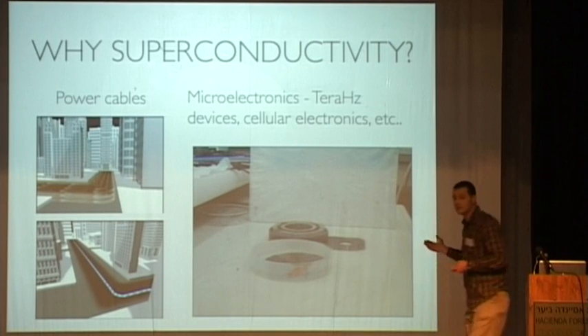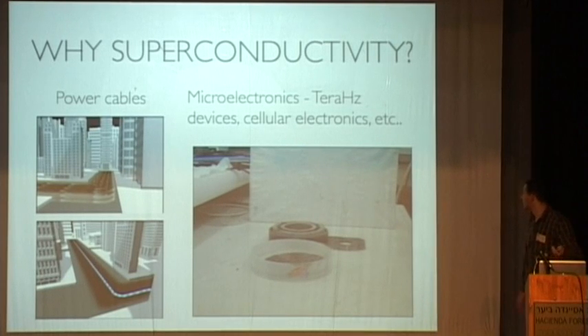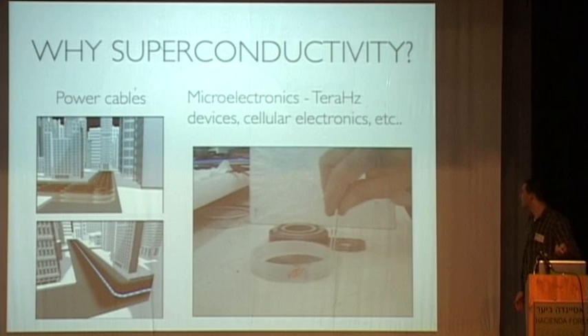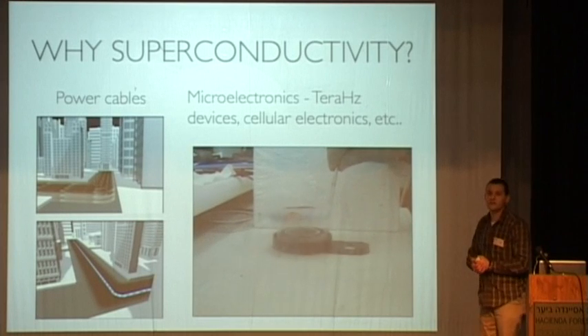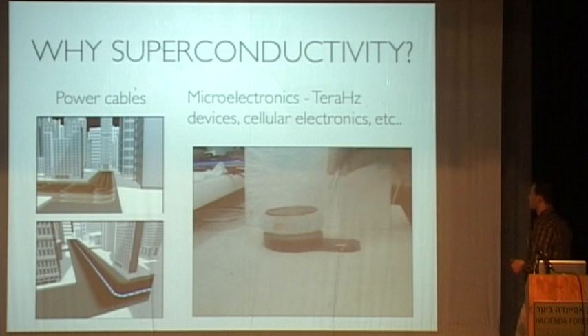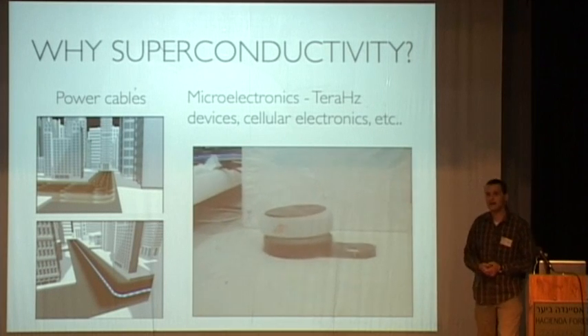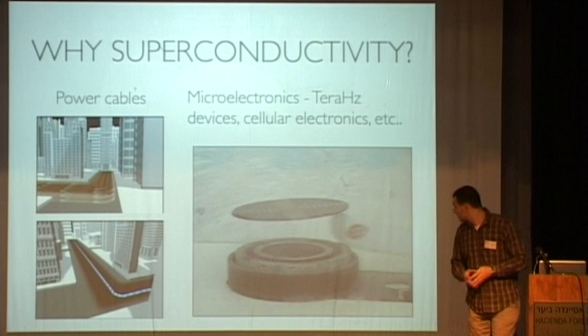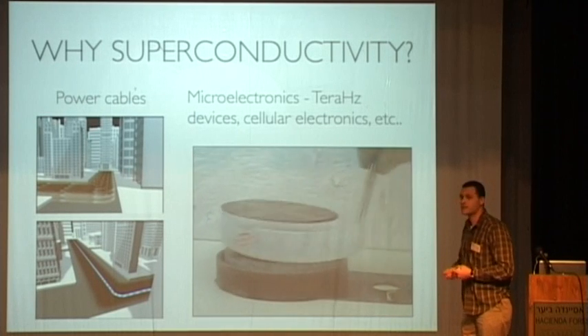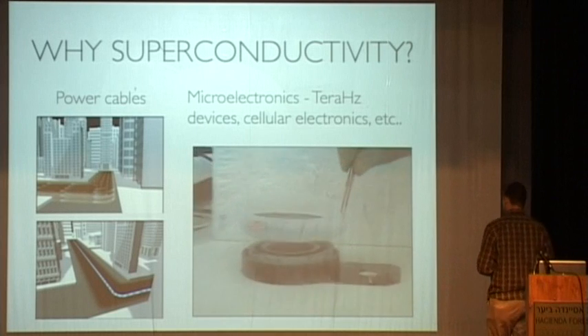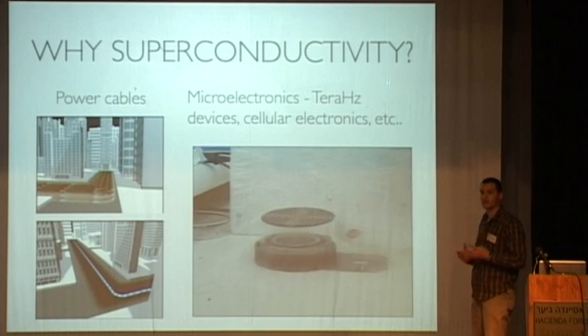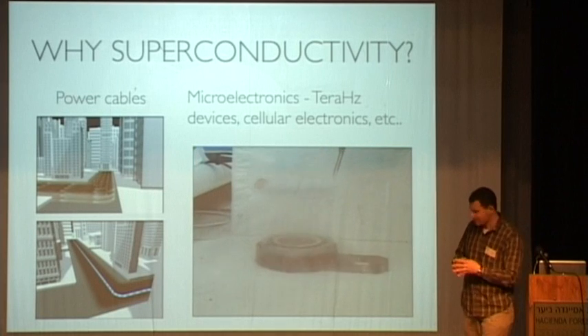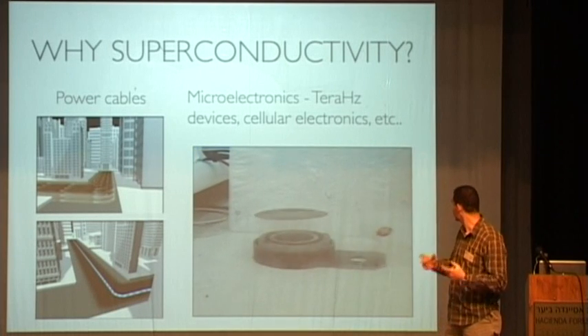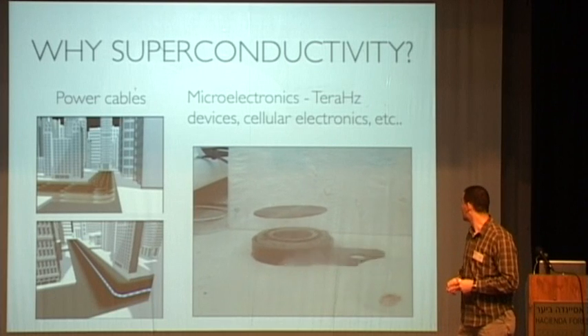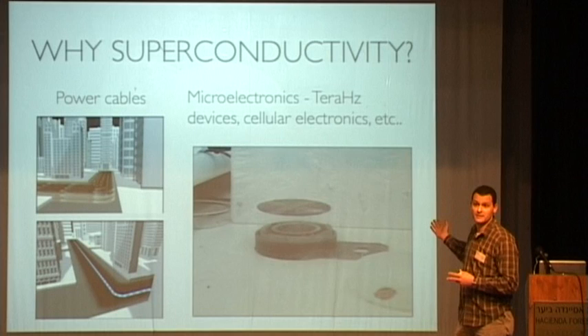And I want to show you an example of a film that we grow in our lab. It's a superconducting film. For example, here we cool it in liquid nitrogen, and then it floats, the property of a superconductor material. It floats above a magnet. It's a very thin film, and you can see that it has very interesting quantum properties. This is not directly related to my talk, but it's a very nice thing to remember about superconductivity and superconducting films. You see, it's very robust, it's floating, it's very unique. And this film is not magnetic.